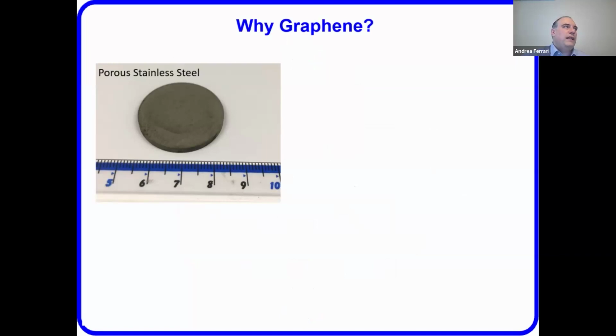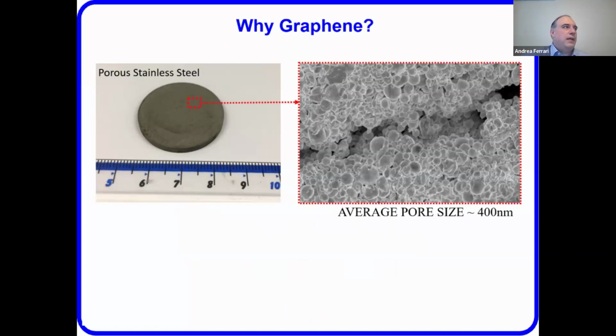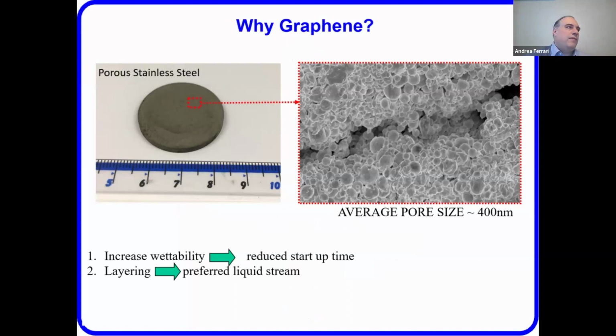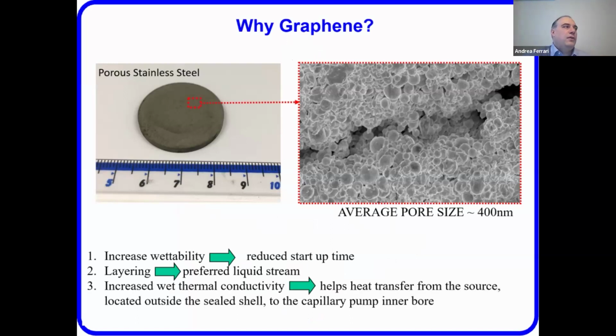So why use graphene in this case? You take this metal wick and put graphene on it. This increases the wettability, so it reduces the startup time. The layering of graphene creates a preferred liquid stream. You increase the thermal conductivity, helping transfer heat from the source located outside the sealed shell to the capillary inner bore of the pump.